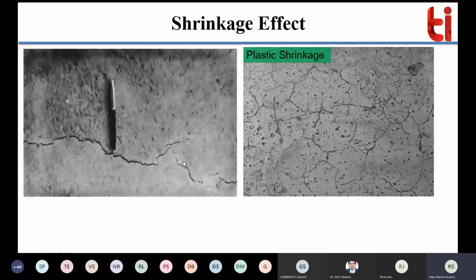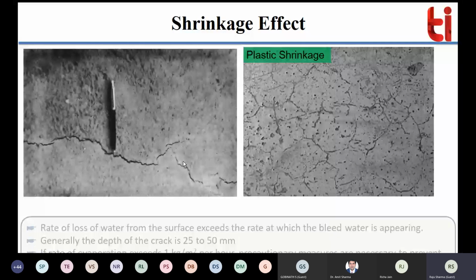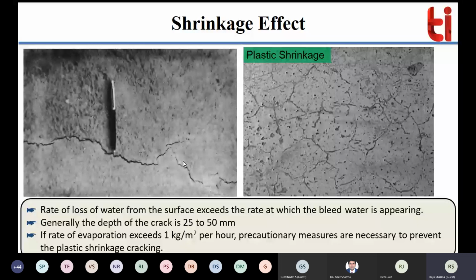So just see closely, the rate of loss of water from the surface exceeds the rate at which the bleed water is appearing. Okay, generally the depth of crack is 25 to 50 mm, and if the rate of evaporation exceeds 1 kg per meter square per hour, right, precautionary measures are necessary to prevent plastic shrinkage cracking. Okay, so this is the shrinkage effect.